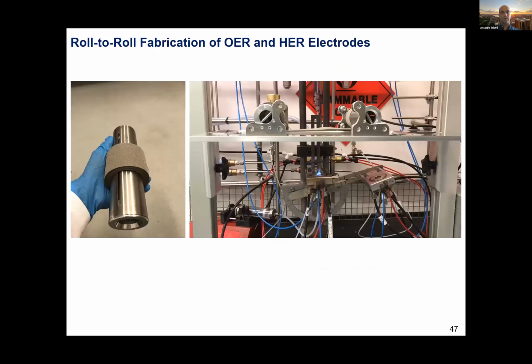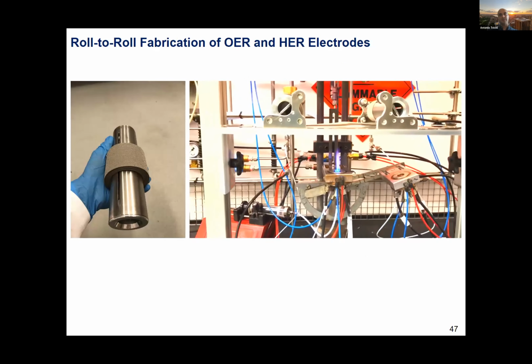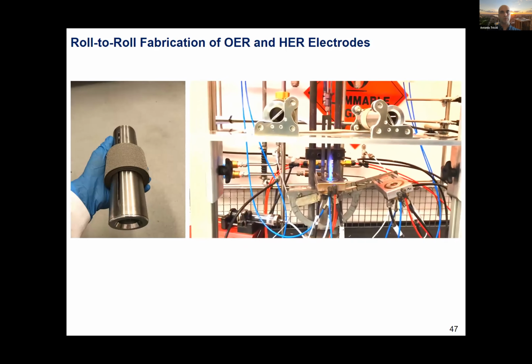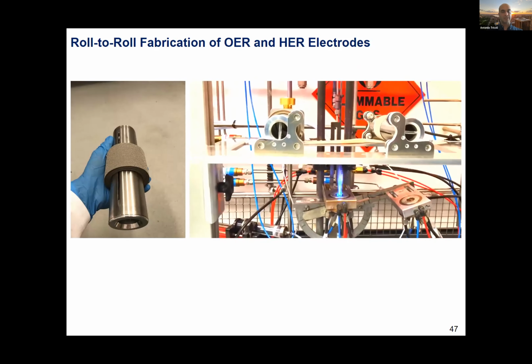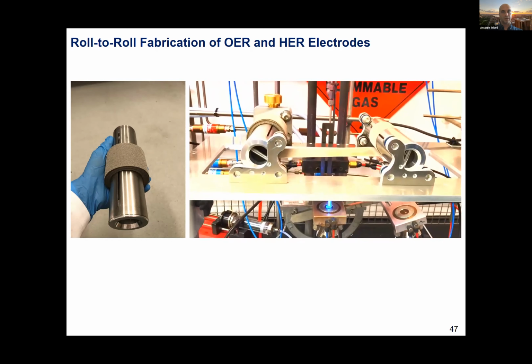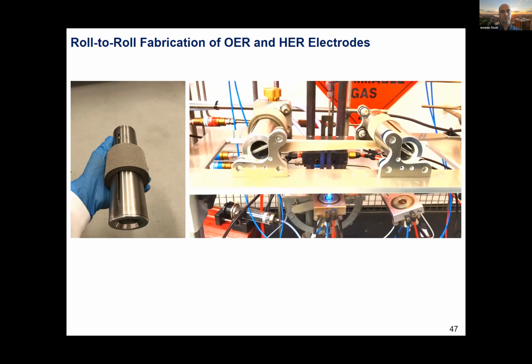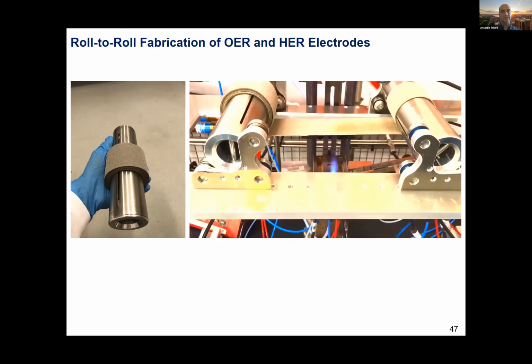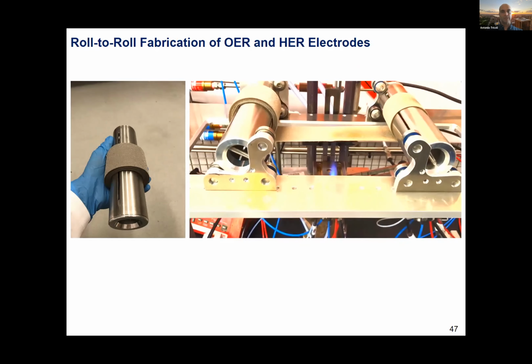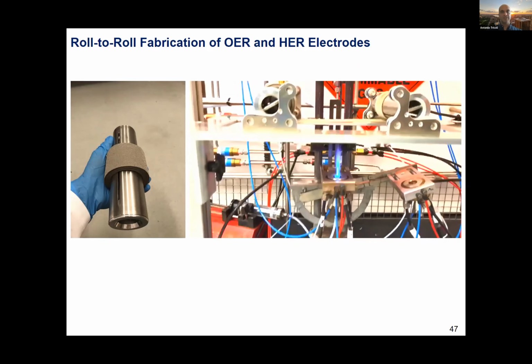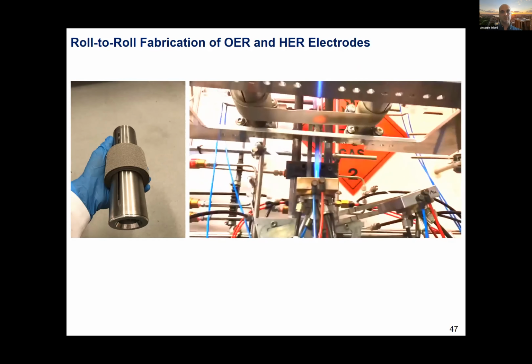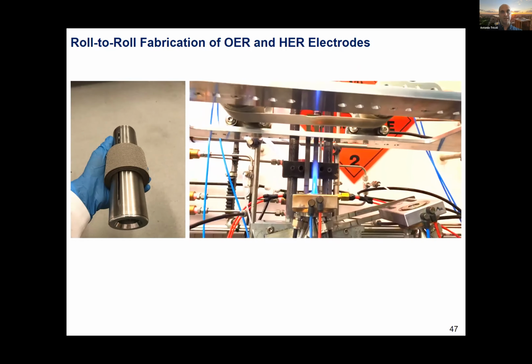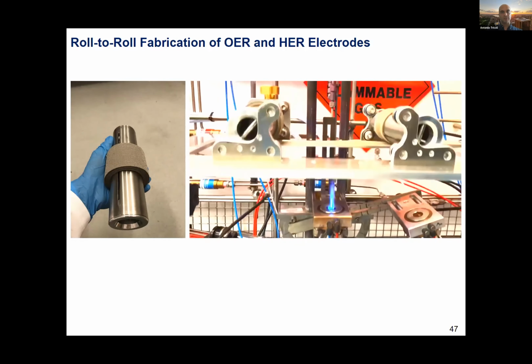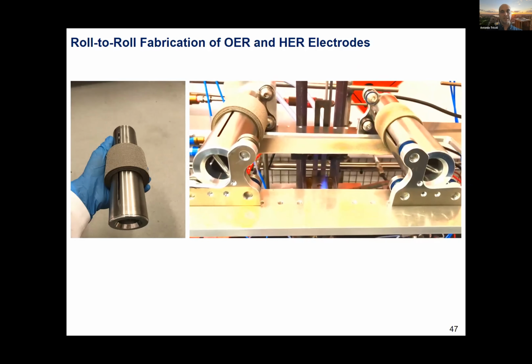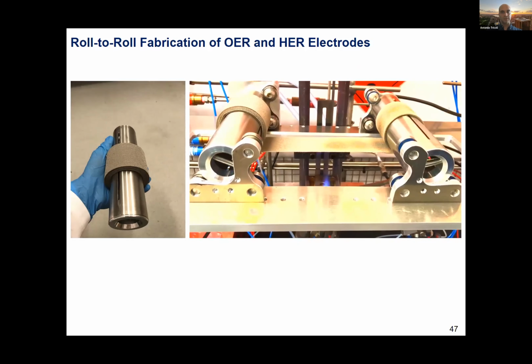And another approach I wanted to show is, instead of using baghouse filtering to deposit on a foam, we can actually do a roll-to-roll production. Basically, we have on one side a rolled foam, which is our electrode, and we have the flame at the bottom. We can use one or two flames, and we can let this roll through. And when we roll, we deposit the material on the surface. And this has been done as a demonstration just with an ethanol flame, so it doesn't produce nanoparticles, and it's a bit smaller so that we can film it better. But we have done it now as a tool for large-scale production of electrocatalysts.